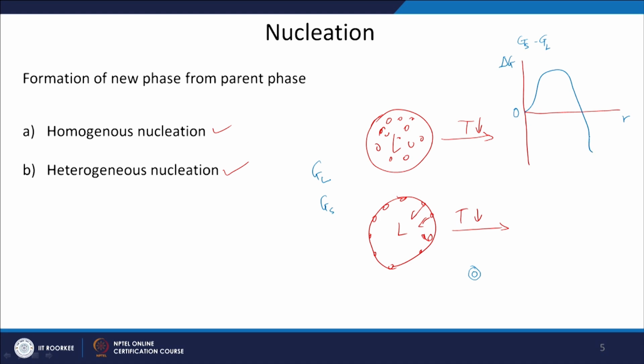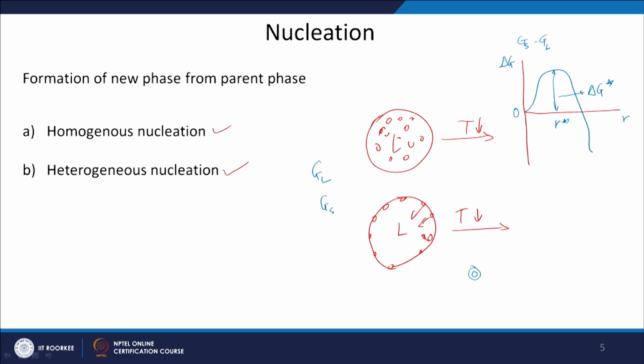My drawing is not very good here, but it will have some curve like this. You can see that initially when the transformation is taking place, the free energy is becoming positive, and then after some time it is becoming negative. This increase in the free energy and reaching the maximum, I will call delta G star, and the radius at which you have delta G star is called R star. I will have a stable nuclei only when I have crossed this hill, and this is what I call the activation barrier.